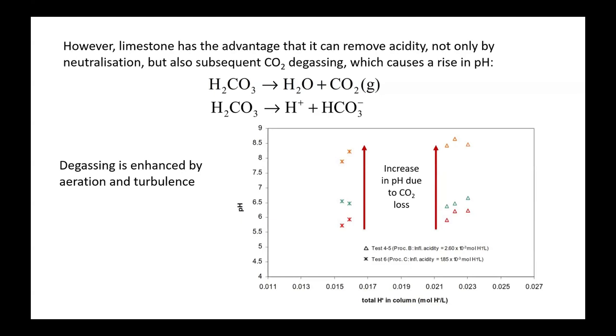And so this is kind of like a gift that limestone gives you if you've used it. After the reaction, if you can degas the CO2 by aeration or turbulence in some way, you'll get a rise in pH that's kind of almost free. And the graph on the right there just shows that you get this increase in pH due to CO2 loss. It's been verified in quite a number of experiments. Next slide.